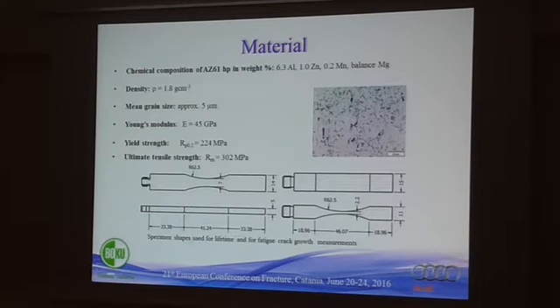So let me begin with only some short comments on the material. As already mentioned in the title, the investigated material was a wrought magnesium alloy AZ61 of high purity. The chemical composition given in weight percentage is 6.3 aluminum, 1.0 zinc, 0.2 manganese and balance magnesium. Remarkable is the relatively fine grain with a mean grain size of approximately 5 micrometers and a relatively high ultimate tensile strength of 302 megapascal.